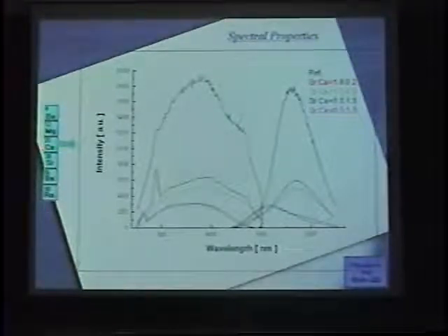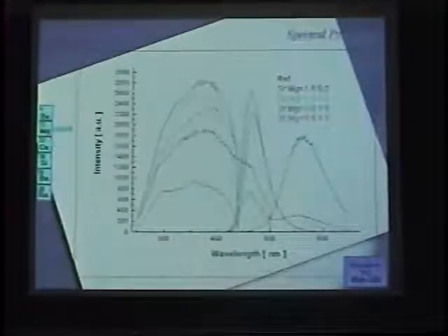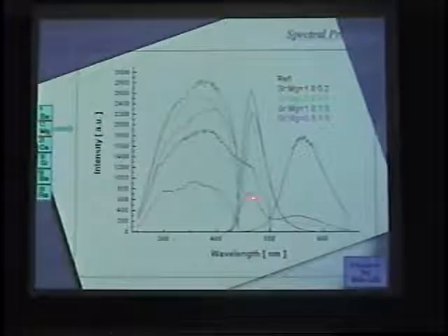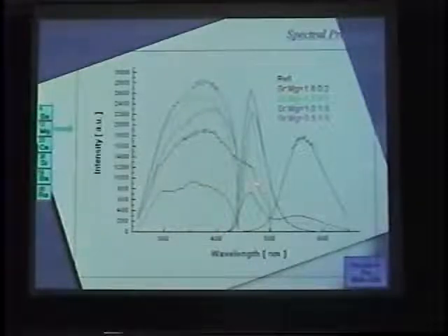In this system we just replace the alkaline earth ions on the cation site and see the wavelength shift to higher energies. But very unfortunately, the efficiency is dramatically decreased in this case. But with Mg ions, something very interesting: the original orthosilicate is near here. What I need is this energy band, which has to absorb a lot of energy and also emit blue or green or red.